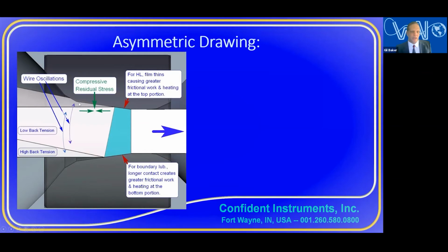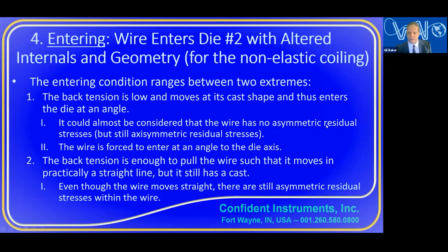There's not really residual stresses because the residual stresses are mostly causing it to curve. And we'll see what happens there. Let me go back to the previous. So it considered no residual stresses, and the wire is forced to enter at an angle to the die axis. Now, the second extreme is the back tension is high enough to cause the wire to move straight.